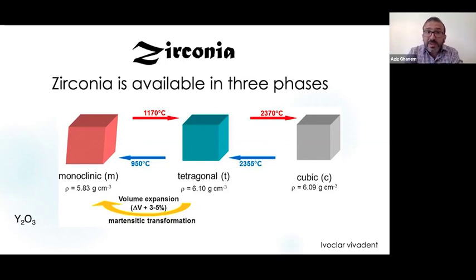Now we're going to talk about zirconia. As an unalloyed material, it is available in three phases, which are the monoclinic, tetragonal, and cubic phases. Each phase of this material has different optical and mechanical properties. But unalloyed zirconia is unstable at room temperature, and tetragonal can easily transform to monoclinic if it is unstabilized. And all the phases are temperature dependent. So for example, if you raise the temperature from room temperature to more than 1170, you get tetragonal, and so on.